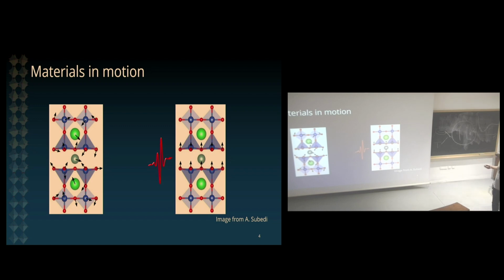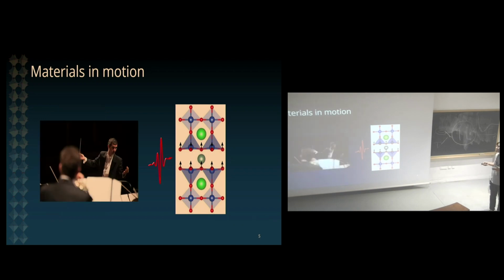So let's visualize something concretely. Let's think about phonons to begin with. We have a material that is sitting at a certain temperature. So there's going to be certain thermal incoherent excitations of the phonon populations of our system, some form of incoherent motion that is present. Now, if I'm able to come in with a light pulse that can be tuned in resonance with a specific phonon mode, now I can impinge a very specific coherent motion to my crystal. So the concept is to come in with a light pulse that can be tuned in resonance with a specific collective mode of the system and bring in a certain organization of its dynamics. I like to think about this as an orchestra conductor that at time zero is bringing in some coherence in the dynamics of a collective.